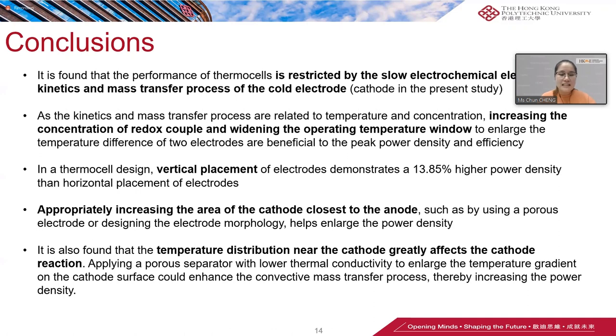It is also found that the temperature distribution near the cathode greatly affects the cathode reaction. By applying a porous separator with a lower thermal conductivity to enlarge the temperature gradient on the cathode surface could enhance the convective mass transfer process, thereby increasing the power density. The further improvement of thermocells requires the redox couple with a higher temperature coefficient, electrolyte with lower thermal conductivity and higher conductivity, as well as electrodes with faster kinetics to maximize the power density and efficiency. They are all the necessary requirements for practical application of thermocells.